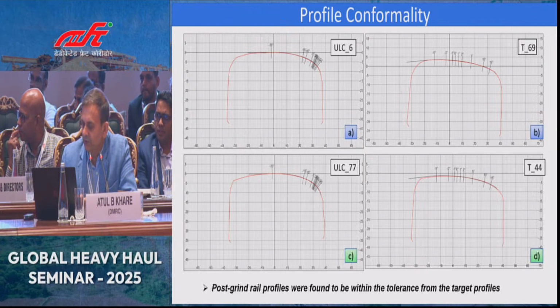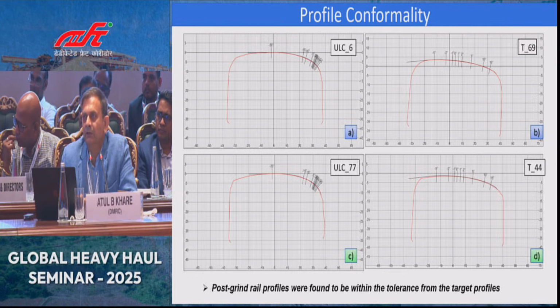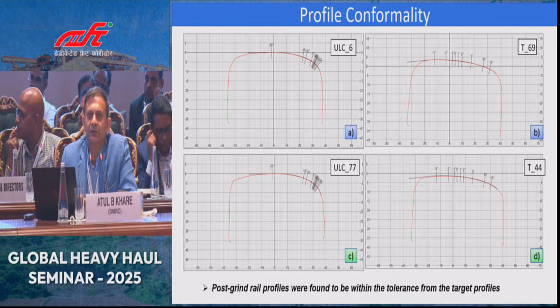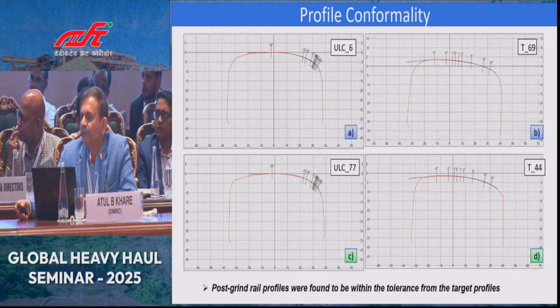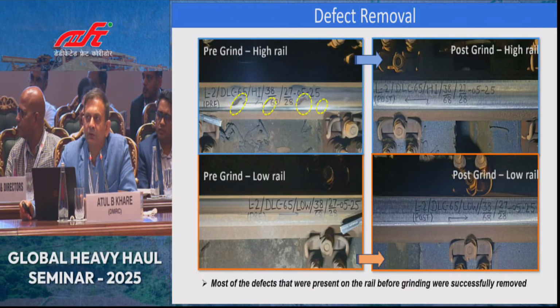What we are doing is measuring the profiles post-grinding, and the profile observed by the mini-prof is confirming the targeted profile. So we have experienced that the grinding is effective. Then there is a photograph at a particular location showing the defects noted pre-grinding, and the right side photograph shows the defects which have been removed.